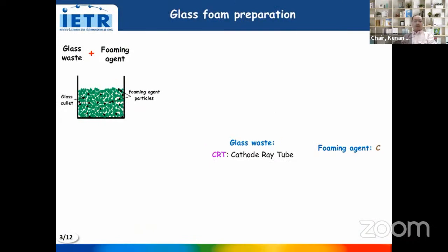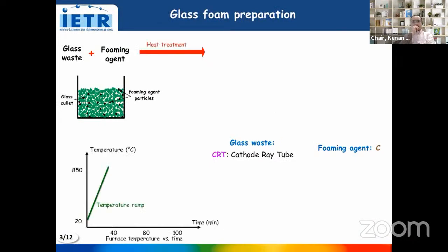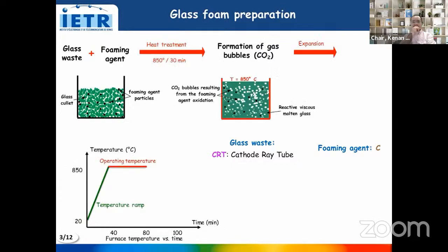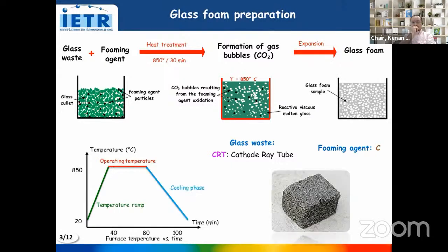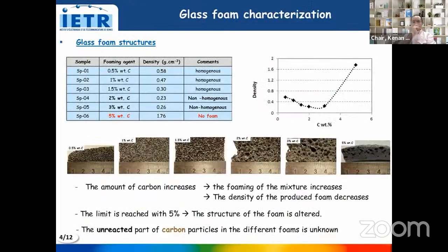For the foam glass elaboration, the glass waste is first mixed with the foaming agent. This mixture is then heated following a three-step process: the temperature ramp, followed by an isothermal temperature step. In this step, the glass becomes viscous and the foaming agent reacts with the glass waste to produce gas bubbles. The expansion and the cooling steps lead to the glass foam production. Different amounts of carbon are used here, between 0.5 and 5%.